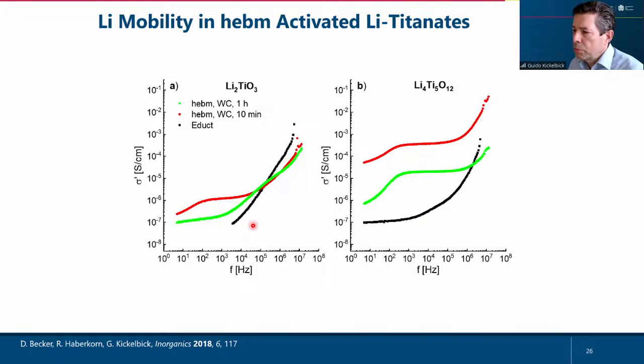And this leads then to higher lithium conductivities. So here you see two examples. These lithium conductivities were measured by impedance spectroscopy. In black, you see the pristine material, and in green and red, you see the high energy ball milled materials. And what you can detect is that you have an increase of the lithium conductivity compared to the pristine materials by several magnitudes.